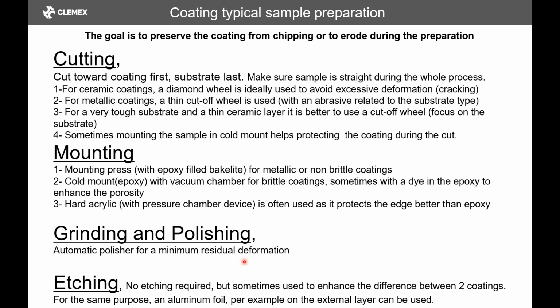Normally, there's no etching required like you would do for grain size, but sometimes if you have a coating that is sensitive to a certain etch and it's the same color as the one that you want to measure, you could use the etchant to darken one of the coatings versus the other one, and then it will be easier to measure. Now you will see that we have various tools that help on this aspect. I remember using aluminum foil on some of the samples to make a white barrier on the edge of the sample exactly for the same purpose.